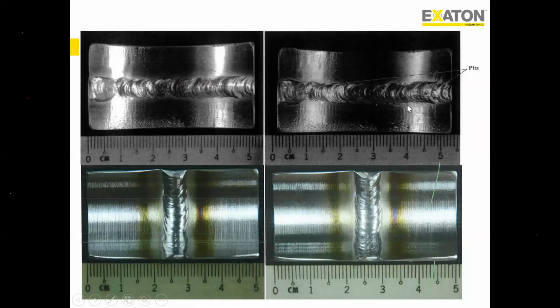The second one is a good example of a really terrible welder skill. So please remember that when you do the welding for the duplex family, try to go for a skilled welder. This kind of weld root has a high potential of pitting. We can go for all kinds of precautions like proper shielding gas, proper filler metal. But if this kind of weld bead appears on the root side, these areas are basically stress risers or sharp edges and have a very high potential of pitting. This one is also a potential risk.